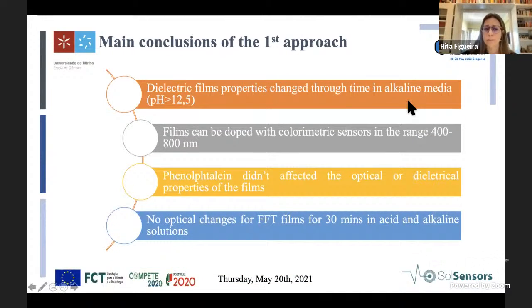So the results obtained with this study allow us to conclude that the dielectric film's properties changed through time in the alkaline environment. The films can be doped with colorimetric sensors in the range between 400 and 800 nanometers. The phenolphthalein did not affect the optical or dielectric properties of the films, and no optical change was found for the films doped with phenolphthalein after 30 minutes in acid and alkaline solutions.